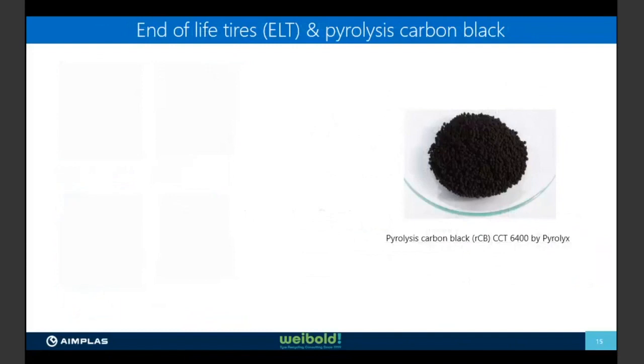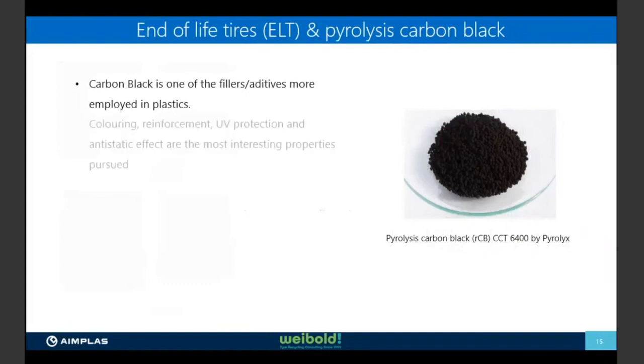And another one is based on the byproducts of pyrolysis. In this case, carbon black. Here you have a sample of carbon black from pyrolysis. And as you know, carbon black is one of the fillers most employed in plastics, also in rubbers. We can obtain color, reinforcement, UV protection, and an antistatic effect. Also, we can improve thermal properties in terms of thermal stabilization. I didn't put it, but we can obtain that at the same time.